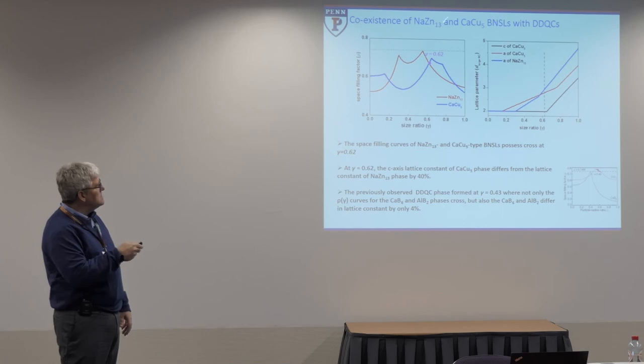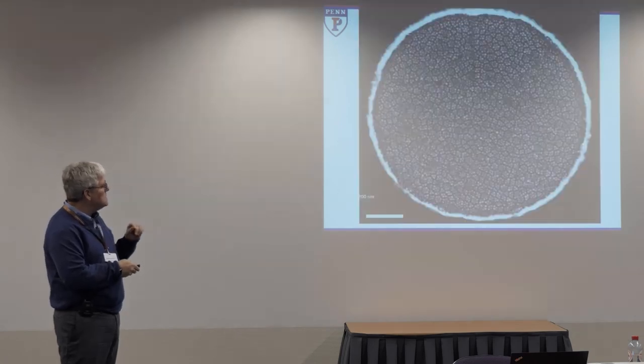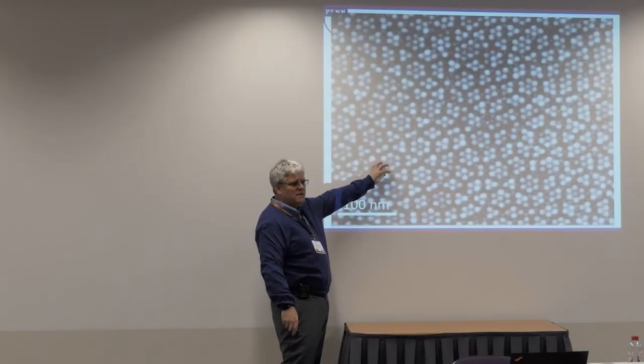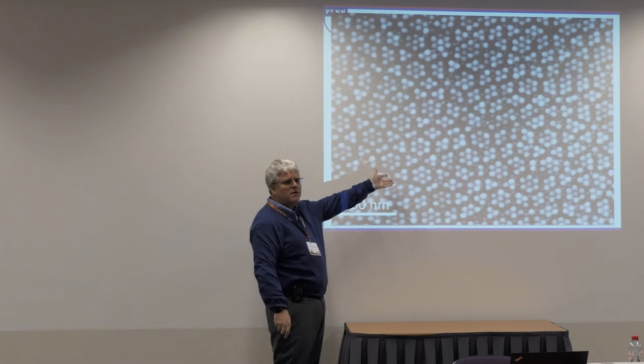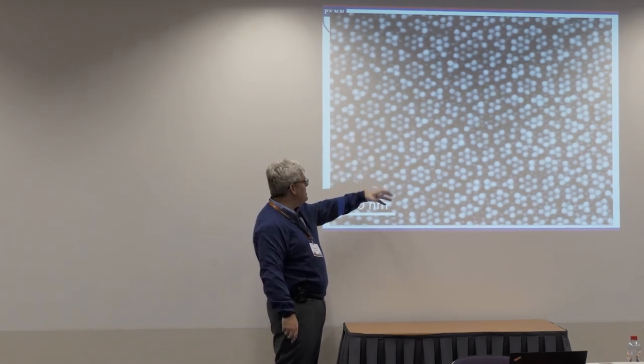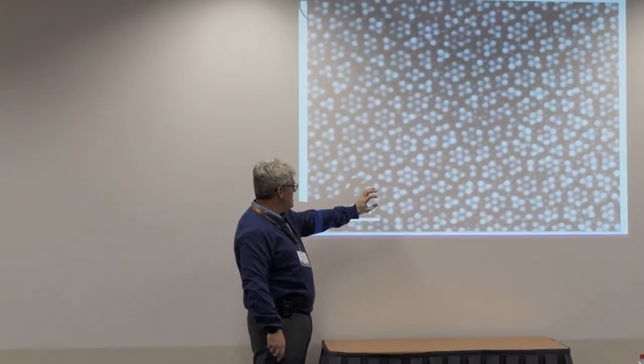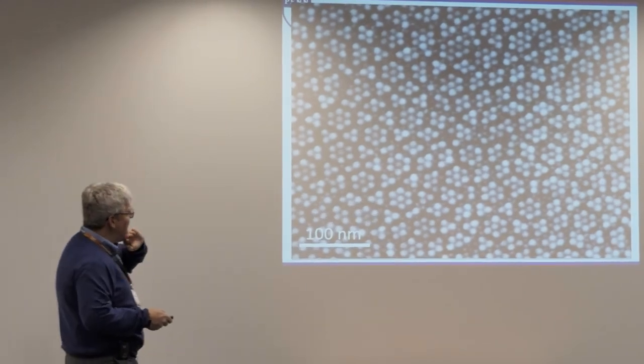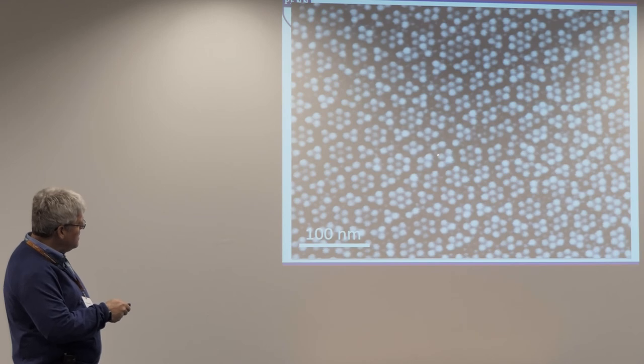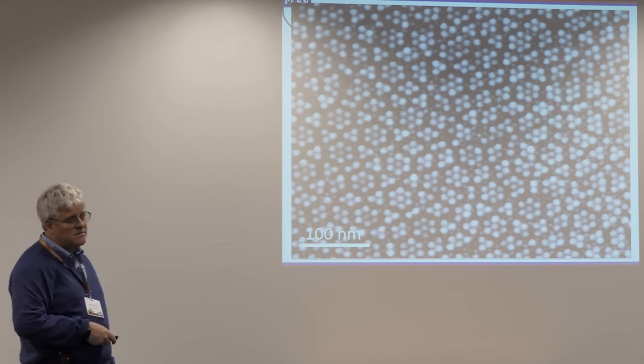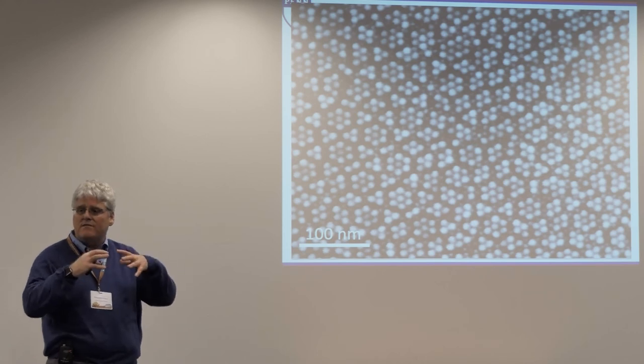And when that happens, you can get systems that form quasi-crystals. So this is a dodecagonal, so 12-fold quasi-crystal. Let me blow it up a little bit. And so it's actually created by small groupings of the nanoparticles or nanocrystals. I use the term nanoparticle when it's not a single crystalline domain or has defects or other parts. Usually use the term nanocrystal for something that is a single coherent crystal domain. But if you look closely at this, you'll see the packing motifs of hexagons and these kite-shaped or diamond-like shapes. So this is the thought experiment of what's often called a Penrose tiling. The systems have symmetries that pack to give relatively high local density, but they don't give long-range translational order.